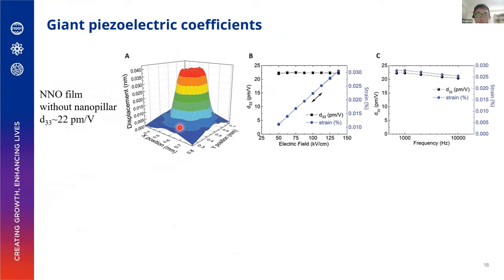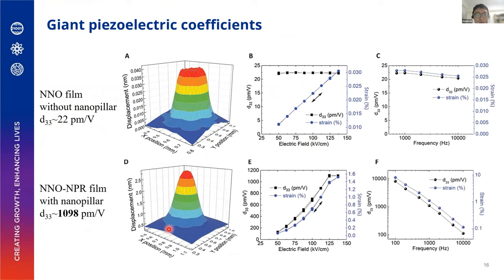Basically, we apply an electric field and we measure the strain, the displacement under the electrode. So for the film without pillar structure, it's a quite normal piezoelectric coefficient, and it's also almost independent of the electric field you applied. However, with this nanopillar structure, you can get a very high, like 50 times higher, piezoelectric coefficient. And this piezoelectric coefficient is actually quite dependent on the field. That's why we think it's quite promising. Maybe we can use this film for frequency tunable devices.